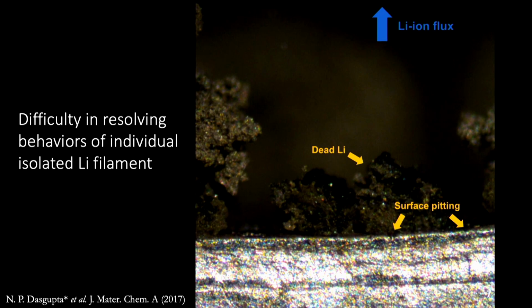This kind of mossy lithium consists of thousands of lithium filaments, and we are seeing it under an optical microscope. As you can see here, it's really hard to tell which filament is connected and which is not. And it's even harder, nearly impossible, to see whether they have any kind of movement. That's why, for the last 30 years, we have formed this consensus that once those isolated lithium become detached from the surface of the electrode, this part of capacity is permanently lost. And we also gave it the name dead lithium.